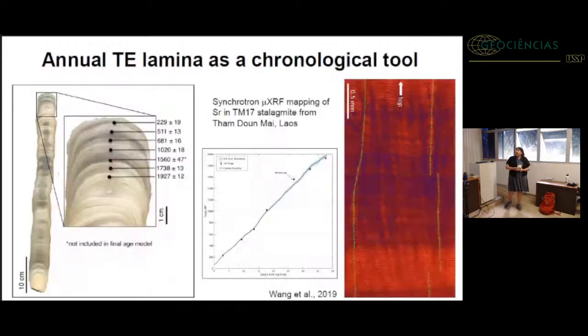stalagmite. As a bit of an aside, another application for trace element measurements, this is a micro XRF, synchrotron micro XRF map of strontium that Andrea collected from a stalagmite that we were working on from Tham Doun Mai, Laos. And we found annual lamina in strontium that were very fine. The growth rate of the sample was around 20 microns per year. So it was hard to see without any other tool. And we were able to use this XRF data to actually count lamina and create a floating layer counted age model, which we were then able to anchor to the uranium thorium age model in order to get this kind of decadal resolution record over the common era.